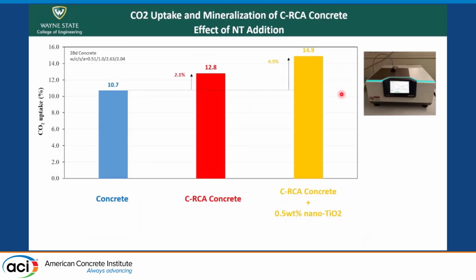Now, what we observed is that by having carbonated recycled concretes, the CO2 uptake increased about 2% compared to the plain concrete. The implementation of nano-titanium oxide inside the carbonated recycled concrete aggregate matrix gave us an addition of about 3% of CO2 uptake.